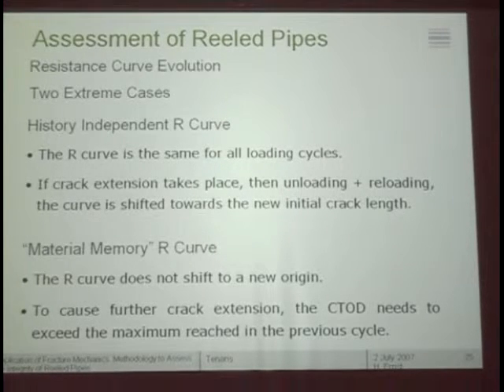They basically said if I have one cycle, I apply the R curve concept, and I determine how much the crack grows at the end of that cycle, the maximum of that cycle. If I unload, come back up again, I forget completely what happened in the first cycle, I move the resistance curve to the new origin, because the crack is a little longer, and reapply the same process again. So I'm shifting the resistance curve every time, forgetting completely what happened before. That's why I call it history-independent resistance curve. That's one extreme case. The other one that we can select is what we call material memory resistance curve.